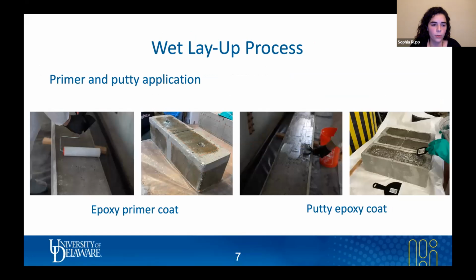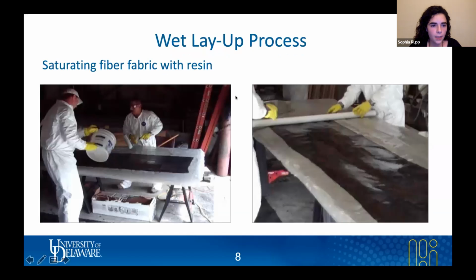After you have those components mixed, you can then prepare your surface for applying the CFRP. This consists of applying an initial epoxy primer coat onto the surface. And then on top of that, you apply that thickened epoxy or that putty epoxy. And what this does is it fills the voids and the pores in the concrete to ensure a good bond between the CFRP and the concrete. And then comes the actual saturation of the fibers to make it a composite material and apply it to the concrete surface. This is typically done with a wet layup process of just pouring the mixed epoxy onto the dry fibers and using a tool to make sure that that epoxy has fully saturated each and every fiber.